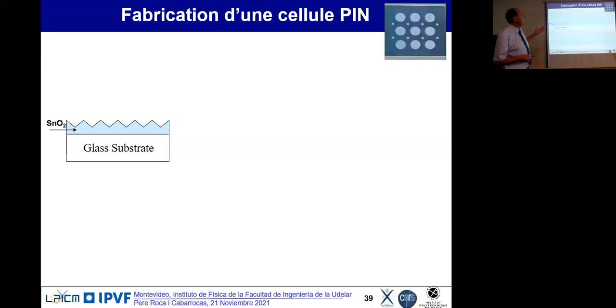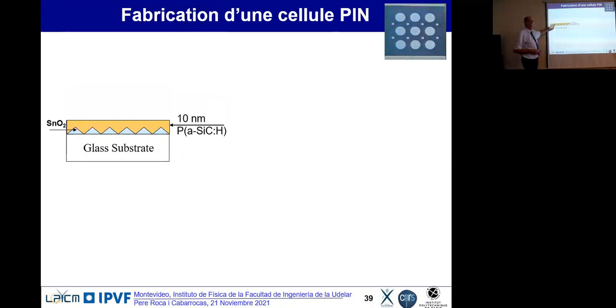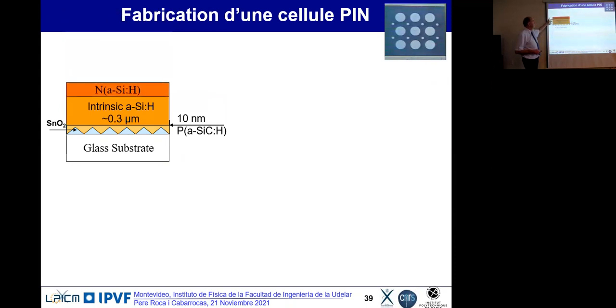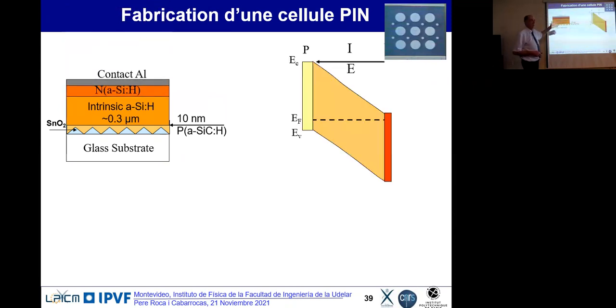If you want to make a solar cell, you start with a glass substrate with a transparent oxide. That would be the same for a perovskite. But now instead of the perovskite, we are going to put the P-type amorphous silicon. So we have a silane and trimethyl boron plasma. Then you just have a silane plasma, then a little bit of phosphine, put the contact, and that's your PIN solar cell, where you have the built-in field between the P-type and the N-type contact. And when you put light, you generate electron-hole pairs, and the electric field removes the electrons on one side and the holes on the other side.